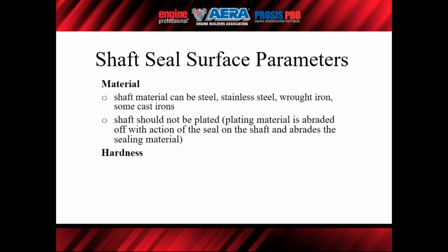The shaft should not be plated. Now this causes a little bit of controversy because there are some plated repair sleeves that go on the shafts, and that's different in the industry, and certain types of seals are run against those. But by and large, it is not recommended to take a shaft and plate the surface that's going to run against what was the original design seal. If that material starts to abrade or come loose, it can really tear the seal up in very short order.